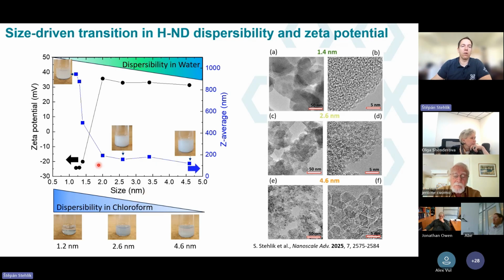When we investigated their properties like Raman and so on, we also investigated the size dependence of the colloidal properties. We tried to prepare colloids by sonication in water, and we realized that when the size was below 2 nanometers, we were not able to get any nice colloids like we are used to with hydrogenated nanodiamonds. But when we exceeded 2 nanometers, suddenly we got quite reasonable colloids. The blue is the Z average size, and the black one is the zeta potential. The zeta potential became positive only above 2 nanometers. The magnitude was not that high, about 30 millivolts, but the colloids became quite stable.